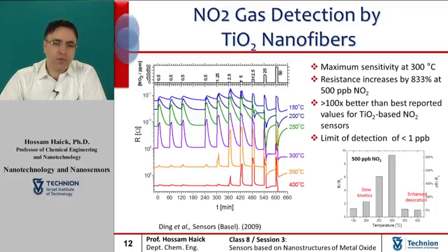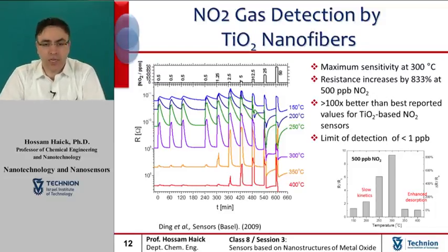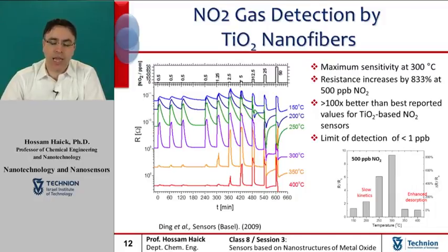The sensitivity of 4 sensor prototypes comprising titanium dioxide nanofiber mats has been tested against traces of nitrogen dioxide, carbon monoxide, hydrogen, methane, and diethyl methylphosphonate vapors in dry air at temperatures between 100 centigrade and 400 centigrade.